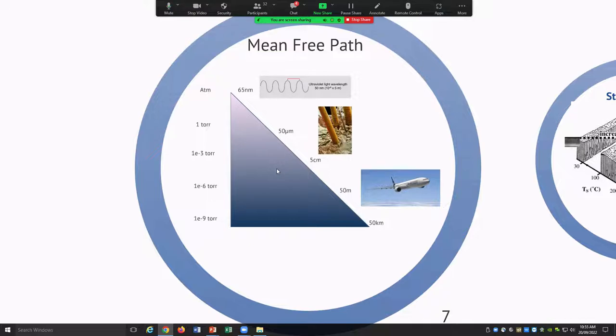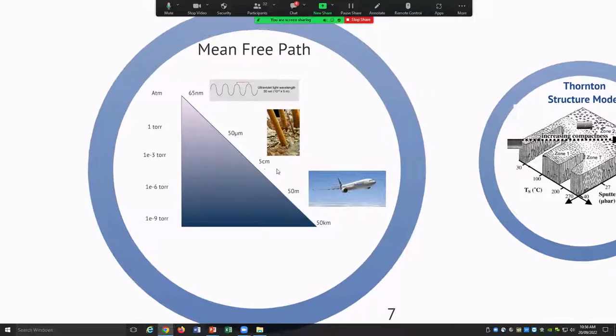So the vacuum allows you to make sure that a particle will arrive at your substrate with the energy that you want and not lose a lot of energy on the way. You also take out all the gases you don't want, take out the water, you take out the nitrogen, water and nitrogen, they're the main ones, and anything else that's in the chamber. So you can control the atmosphere and you can put back in the gases that you do want, the working gases or anything else that you do want, or oxygen. So vacuum to control the environment and to control the energy of the particles as they arrive.